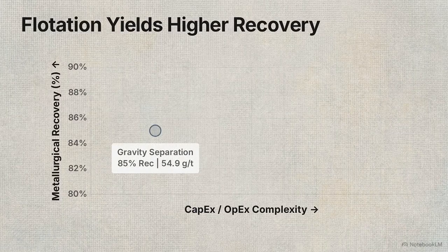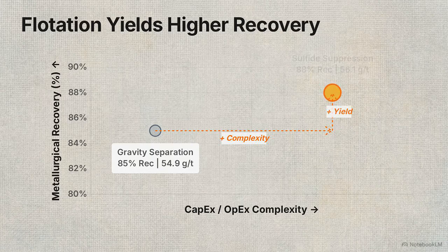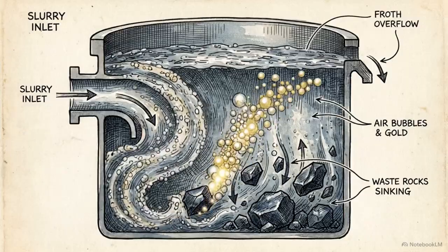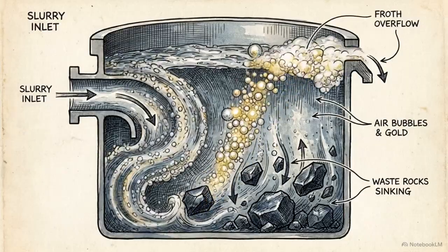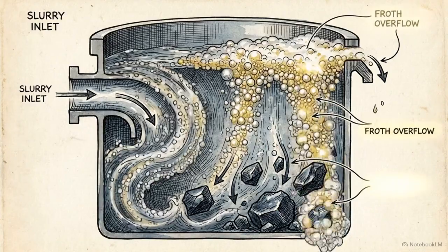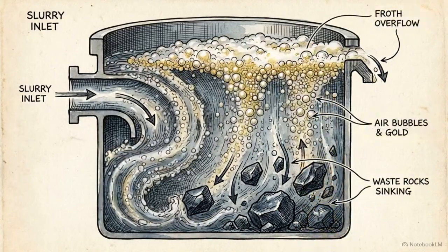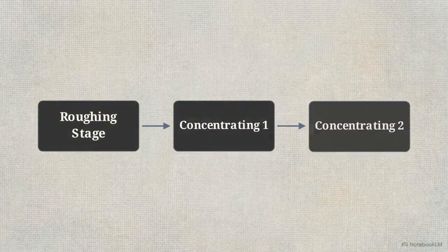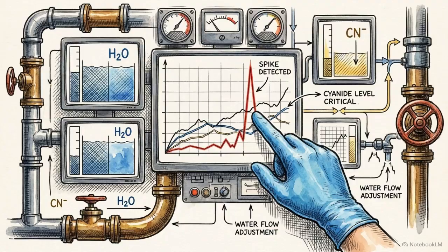Moving further right on the complexity axis, sulfide suppression flotation increases the metrics to an 88% recovery at a 56.1 gram per ton grade. This method introduces chemical reagents to the slurry to suppress the waste sulfides while allowing the gold to float to the surface for collection. The circuit requires a 3-stage process, 1 roughing stage followed by 2 concentrating stages. This achieves a higher recovery than gravity, but it requires much stricter chemical management and process control.